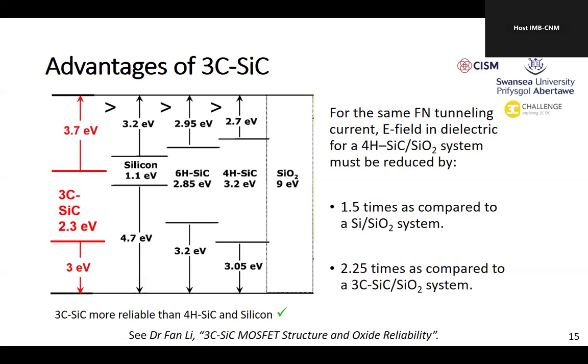It's a different polytype. Commercial silicon carbide is obviously hexagonal, 4H, repeating after 4 bilayers. But for cubic silicon carbide, this diagram shows the band offset between the semiconductor and silicon dioxide. It's even better than silicon. Amador and I were discussing this on the way here. This material is not as wide bandgap as 4H, so it's not going to have as good a trade-off between on-state resistance and breakdown voltage as commercial 4H. But in terms of gate oxide reliability and MOS interface quality, it should be much, much better.